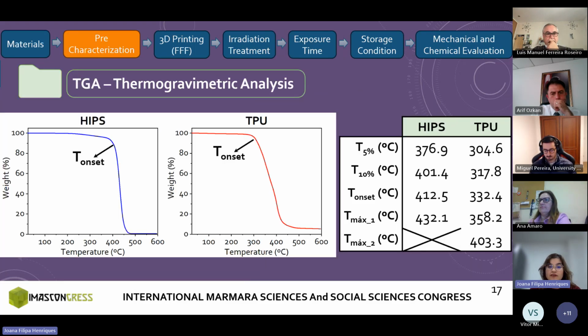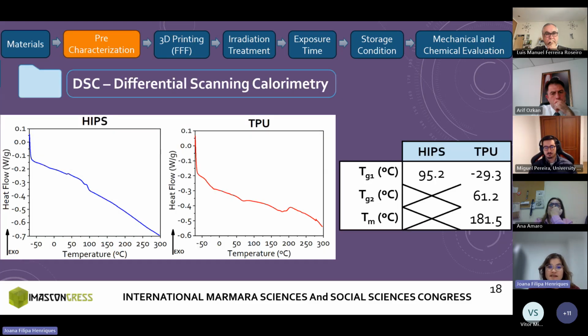Then, the thermal stability of the filaments was studied and the results showed that both materials are stable for temperatures below 300 degrees. While HIPS presents only one stage of degradation, TPU presents two stages of mass loss. Next, DSC was performed to study the thermal events of the polymeric materials. In the case of HIPS, only one thermal event was identified, and on the other hand, TPU presents a melting temperature and two glass transition temperatures could be identified.